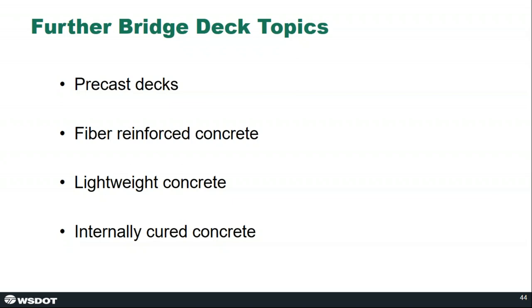These decks can be prefabricated using very durable concretes, high strength as well, and it allows for rapid construction. The challenge with these systems is oftentimes the field connections. These generally won't have the same durability as the bulk precast concrete. They often lead to ride issues. And so there's a few ways to deal with those. You can overlay it after the fact with the cast in place system, or you can pre-overlay and grind. So there's certainly some potential here, but we tend to prefer cast in place bridge decks when we're very focused on lifespan of our bridge decks.